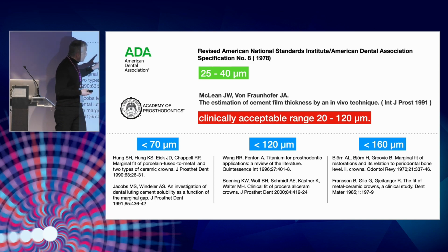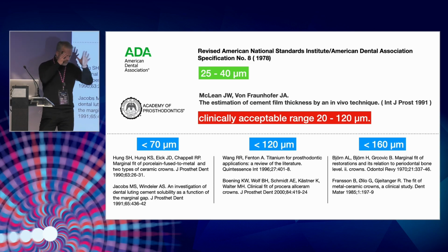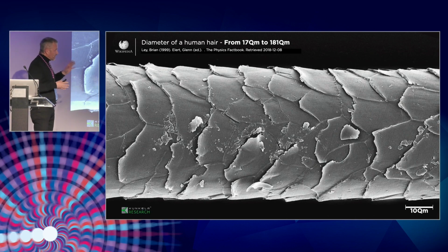Our recommendation is that the clinically acceptable range is between 20 and 120. We need a space for removing our debonding and luting agents after the restoration. That's why it starts at 20, but 120 is recommended as the maximum for drying of the restoration. And this range is exactly the thickness of a human hair. This is how stressful dentistry is, because we are balancing on this super precise thickness. True, for example, African people have thicker hair, while Scandinavian Norwegians have thinner hair, but still we are in this thickness.